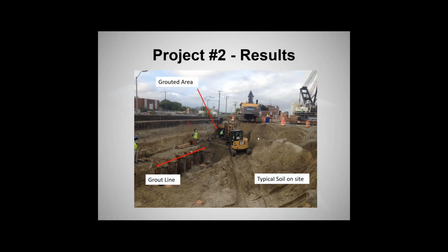So what does this look like when you do it? This is the site later on. I guess the important thing is you can see the grout line, the red line that was just behind the sheet piles on the left-hand side of the page. On the right would be the typical soil conditions without grouting on the site. And you can see, it's a sand and it goes in at a typical angle of repose for sand when you excavate it. But the interesting thing probably to show here is this grouted area along the back of the picture where the guy is working, installing some lagging boards, because that's a cut through the grouted material.